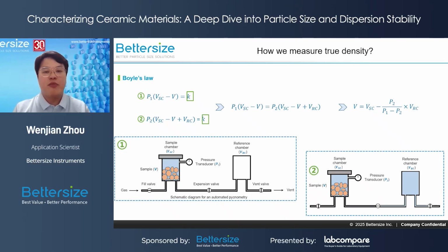Next, we open the expansion valve, allowing the gas to flow from the sample chamber to the reference chamber. Once equilibrium is reached, the pressure is measured as P2. Suppose the volume of the sample is V, and we can use Boyle's law to obtain two equations. The volumes of the sample chamber and the reference chamber are already known, along with the recorded values of P1 and P2, so the volume of the sample can be calculated by the software. With the sample's mass easily obtained with a precise balance, we can then determine the true density.